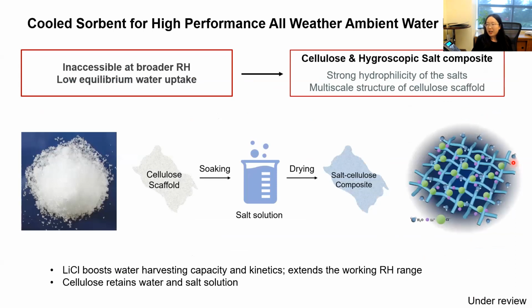Because of this challenge, we wanted the material to work in all weather conditions, even in dry regions, because dry regions are the regions that need the technology. And we were trying to incorporate salt into the cellulose fabric. The process can be very simple: you can just take a cellulose scaffold like a fabric, soak it in a salt solution, and then dry it.